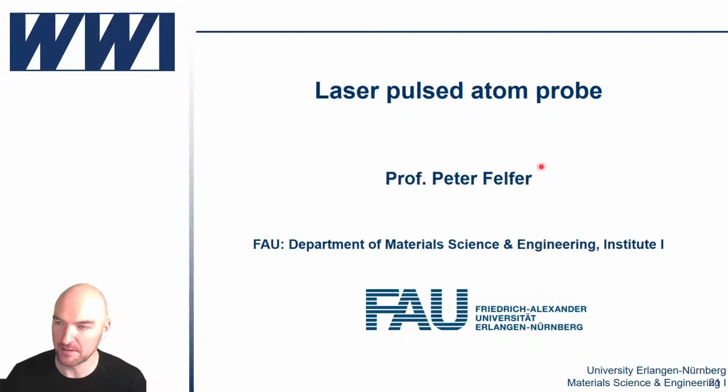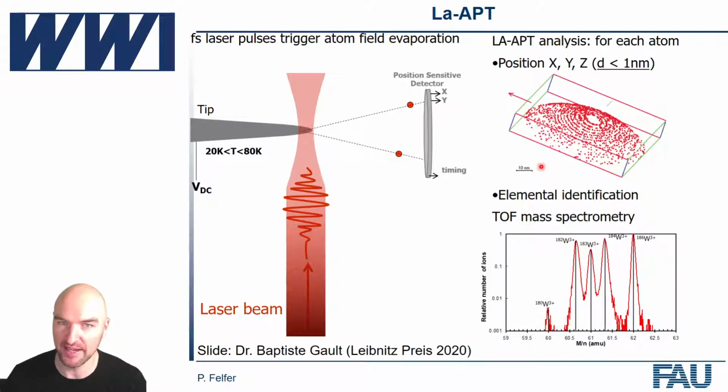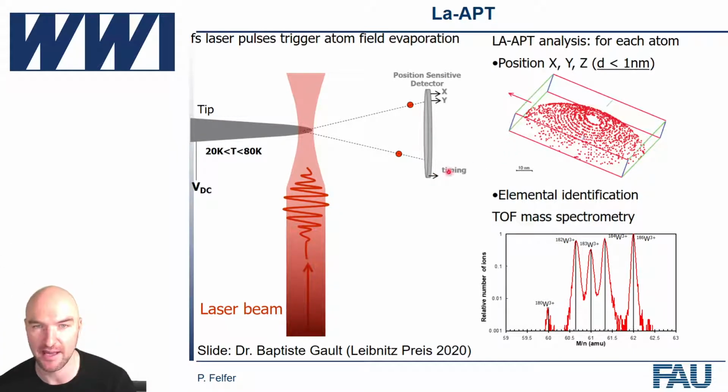So we need laser atom probe because in this case, we don't change the field. The field, we put in via DC voltage, so very slowly. And through this very slow process, charge hopping on the surface and other surface conductivity effects are going to be more than good enough to get the potential to the tip of the surface. And then we'll just increase the temperature and get the time correlation from this increase in temperature.